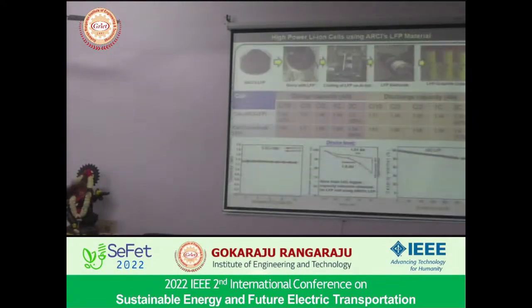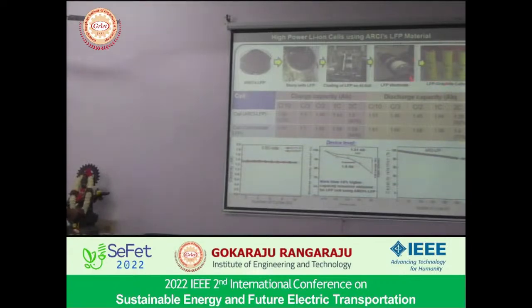That is the reason we got that good capacity even at fast charging also. So finally, whatever the material which we developed is going to be used for making lithium ion cells. We made actual lithium ion cells using our Chennai facility, using commercial graphite as an anode and ARCI LFP as a cathode. This is the LFP graphite cell which we made. And also we compared the cell which is made from the commercial LFP. That would be the apt comparison.